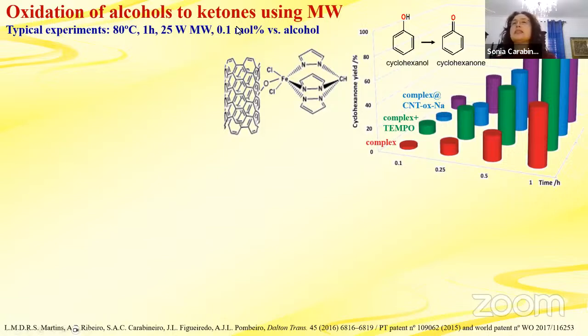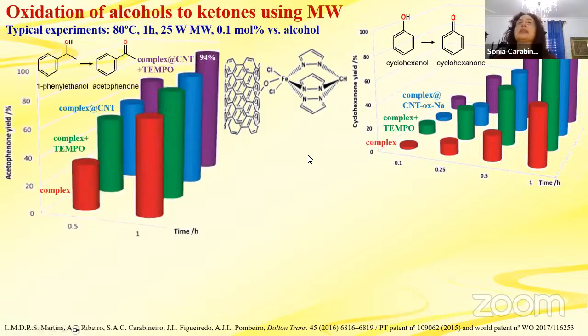And you see here, this is the iron complex. So this complex here alone has these yields. So we are seeing it here with time. Okay, so 1 hour was the best yield. So we have here only the complex. If we add the radical tempo, it increases. If it's heterogenized, it's even better. And of course, the best result is heterogenized, and with the tempo radical, we obtain a yield of 98%. Okay, so this was for cyclohexanol.